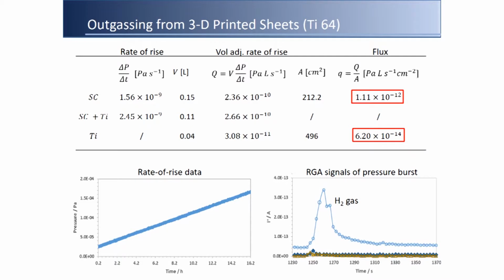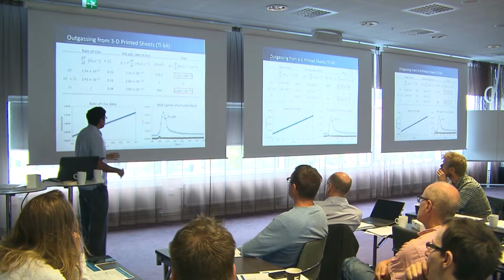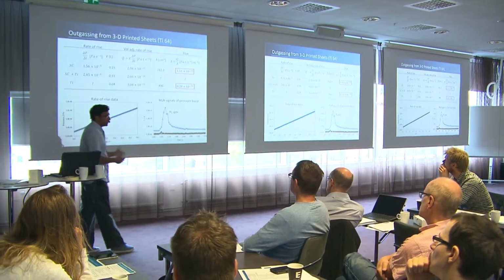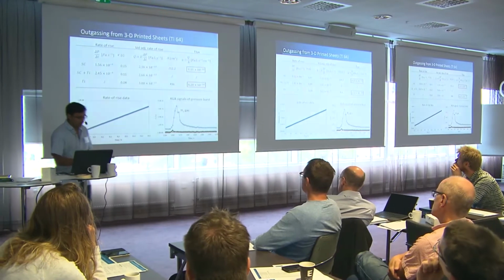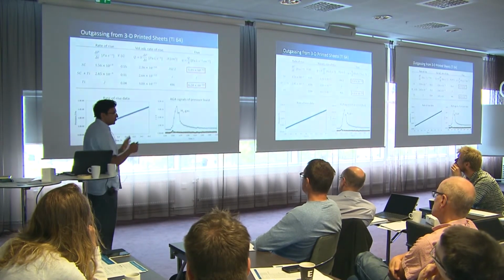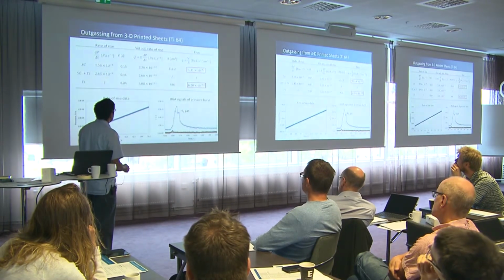So let's look at some of the data. When you look at the rate of rise, the first thing you notice is the sample chamber is pretty much on par with the titanium sheets, even though the surface area is so much larger. In a way, that's good news, but from an engineering perspective, the number you care about is the flux, and you can see the flux for the titanium part is significantly lower than stainless steel, which is the good news here, right? This is what you expect to see. What's coming off of it is mostly just hydrogen gas. So again, these are all good news. That seems to say, all right, we should be fine for using these for these purposes.